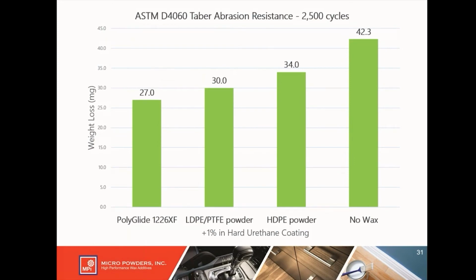So here are Taber abrasion resistance results, 2,500 cycles, and we're looking at weight loss. So the less weight removed after 2,500 cycles, the better. On the right, this is a hard urethane coating with no wax additive. We removed 42 milligrams. Next to that is just a micronized high-density polyethylene powder. It's better at 34 milligrams. Next to that is a low-density polyethylene PTFE composite powder. So there's your PTFE, and it's better than the high-density polyethylene, so 30 milligrams. But on the left, Polyglide 1226XF, PTFE-free, high-density polyethylene ceramic composite powder, the best, 27 milligrams of weight loss in the Taber abrasion test.